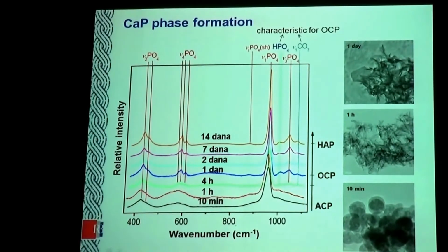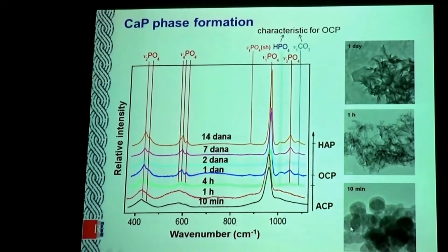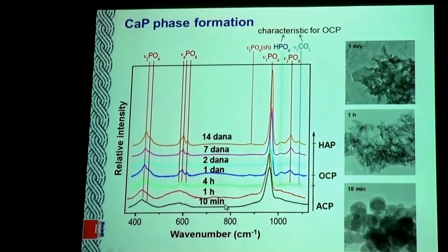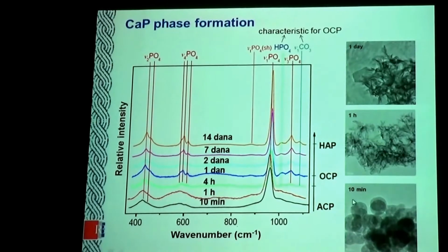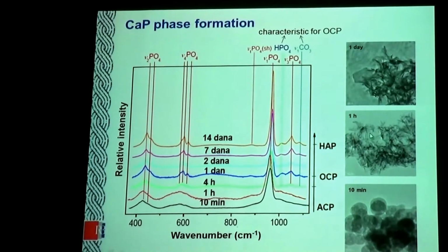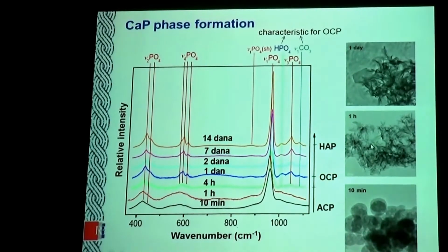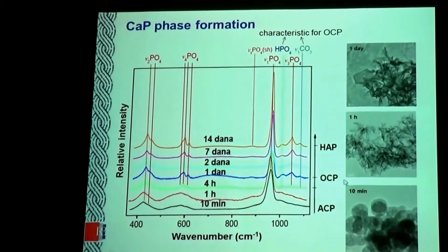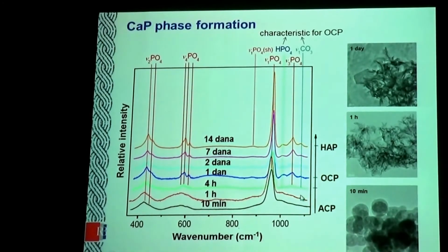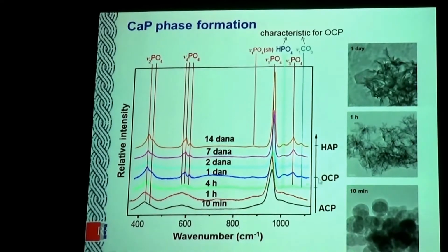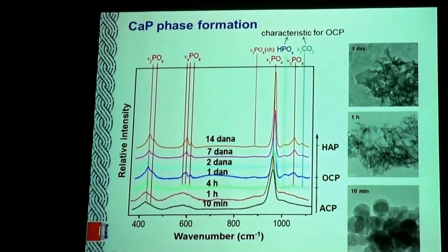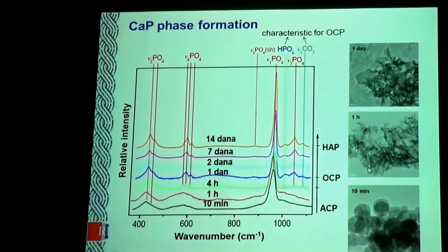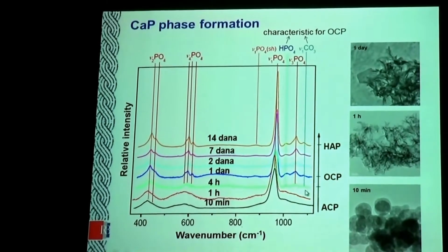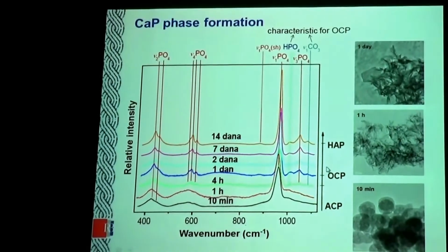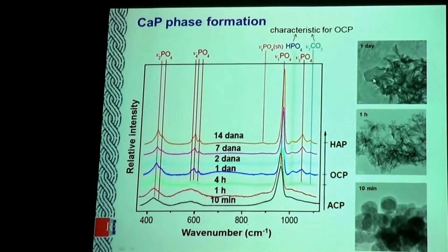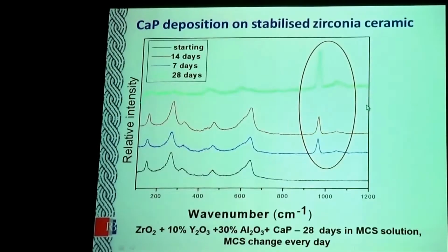This is the TEM observation. After 10 minutes we still have amorphous calcium phosphate, formation of octacalcium - just seeds of octacalcium can be recognized as very small bands, and here you see the morphology which belongs to such seeds. After 4 hours or 1 day we already have a completely formed octacalcium phosphate.